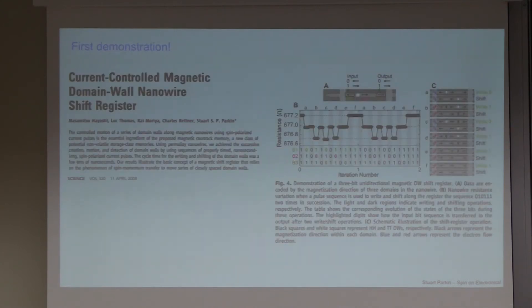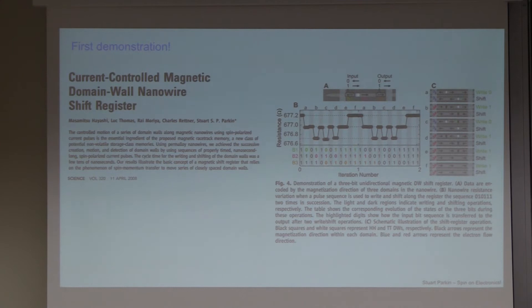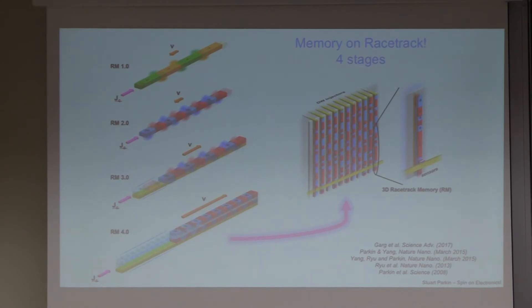When we first started this concept, the way of manipulating magnetization was essentially based on two ideas: one by Neville Mott in the 1930s — that an unpolarized current from a battery entering a magnetic material automatically becomes spin polarized, because up-spin and down-spin electrons scatter at different rates, leading to about 60–70% polarization in simple magnetic metals like nickel, iron, and cobalt. When you pass a current into a magnetic wire, the current is carried by electrons of one spin orientation, and by transferring spin angular momentum from those conduction electrons to the domain wall, you can move the domain wall. We demonstrated this in a science paper — the first demonstration of a current-controlled magnetic domain wall nanowire shift register where domain walls were detected by resistance. I like to call this racetrack memory, the first edition.